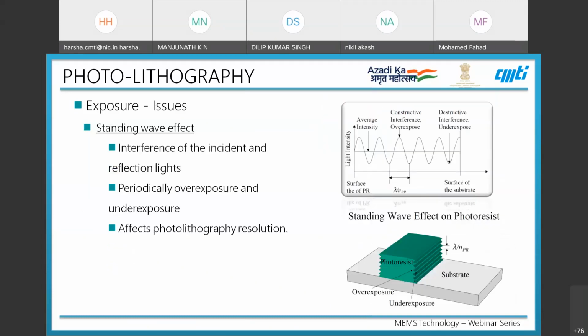While we do the exposure process, one important issue that arises is the standing wave effect. What is the standing wave effect? The interference of the incident and reflected light when we project a light source results in a standing wave effect. As shown in this image, there is a surface of the photoresist and a surface of the substrate. In between, as the light passes through, the average intensity expected is at the center.